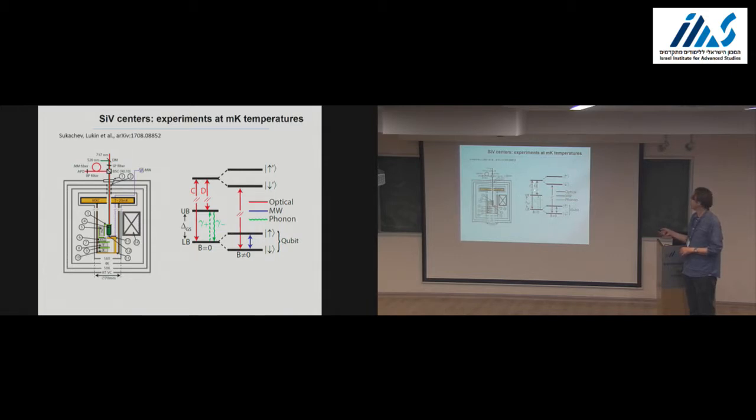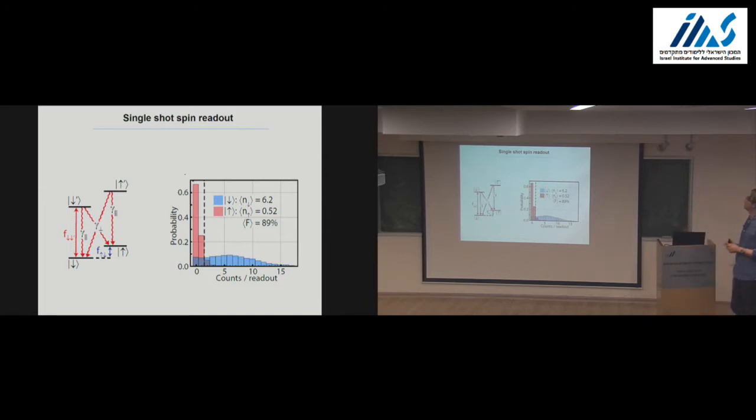So if you come to millikelvin temperature, everything freezes in the lowest energy orbital state, and now your spin states do not get affected by the relaxation between orbital sublevels. And so experiments of this type, who performed them? The first one was at Harvard at about a few hundred millikelvin temperature, where an optical microscope was placed in a dilution refrigerator. And so there is quite a significant improvement of the spin properties of these defects.